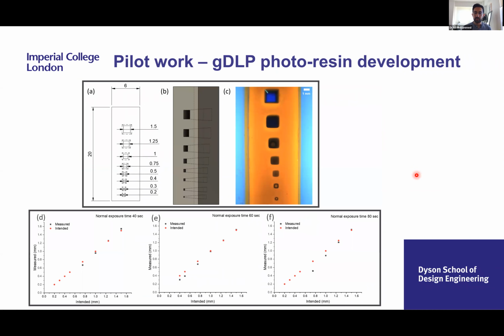Next, this is some work Livia was also doing. Once we had the formulation that was working, she looked into creating this study where you find the minimal channel size that you could physically print with the setup and with the printer, as well as the resin. Here you can see that at 40 seconds we had under curing, at 80 seconds we had over curing, at 60 seconds was the sweet spot where the measured, which is the black dots, were very similar to the intended, which are the red dots. And we actually got to 300 micron channels. So we can print complex structures with 300 micron channels.